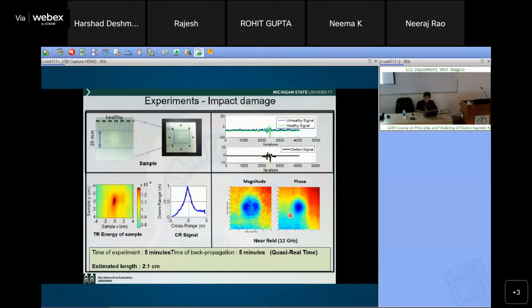And we got the same thing from a near field. At 12 gigahertz, you get very good results. There's the magnitude and the phase image of the S21 parameters. But it takes a much longer time. Well, I shouldn't compare the time right now, because time reversal is a simulation that takes time too. These are early days. At this point, we're just looking at feasibility, whether this kind of approach is feasible. That's all we're looking at.